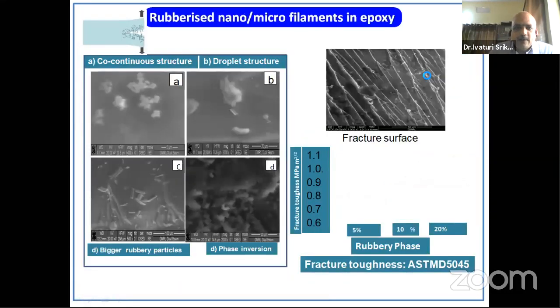By optimizing the ratio of this rubbery matrix to the conventional matrix, you can see here the rubbery matrix dispersed in a conventional matrix. So we could get a very good improvement in the fracture toughness. Fracture toughness is an indication of strain to failure, or the toughness of the matrix. Here you can see the fracture surfaces, which show riverine surfaces. If it is very glassy, that indicates poor fracture toughness. By adding this rubbery reinforcement, you can see the riverine marks on the fracture surfaces, which indicates it has acquired good toughness.